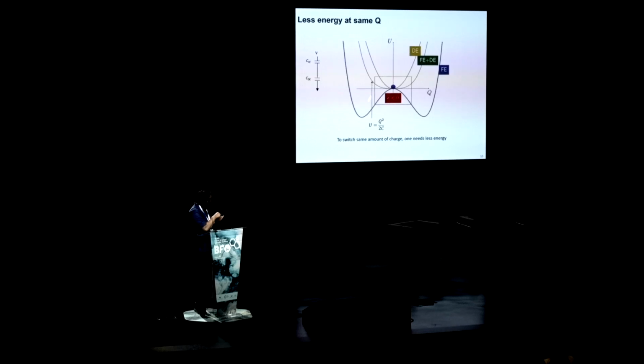So if I do that, what happens? If I look at this composite energy landscape, I can see that to switch the same amount of charge, x-axis is charge, I need a smaller amount of energy compared to my dielectric, right? And so if I look at U equals Q square over twice C, this means that for the same charge, if energy is lowered, my capacitance has gone up. Now, this is not surprising because, again, thermodynamics told us that for the transition in this collective order-dominated region, I would need a smaller energy. So what I'm seeing here in the energy landscape is basically the manifestation of that thermodynamic principle.